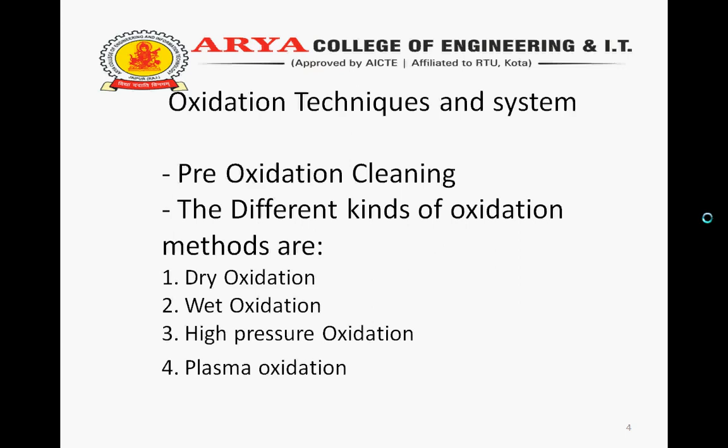Second is wet oxidation. Wet oxidation can be carried out by pyrogenic techniques, which react H2 and O2 to form water vapor. The microprocessor controls the H2 and O2 mixture. The pyrogenic technique assures high purity steam provided that high purity gases are used. If wet oxidation by the bubbler technique is used, a carrier gas is typically flowed through a water bubbler maintained at 95 degrees centigrade.